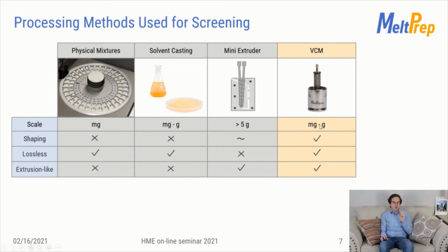VCM fulfills all the listed requirements. With vacuum compression molding, one can prepare samples starting from a few milligrams, comparable to solvent casting, and one can go up to the low gram range, always mimicking hot melt extrusion behavior. One obtains perfectly precise shaped samples in a lossless way, perfectly suited for the development tasks.